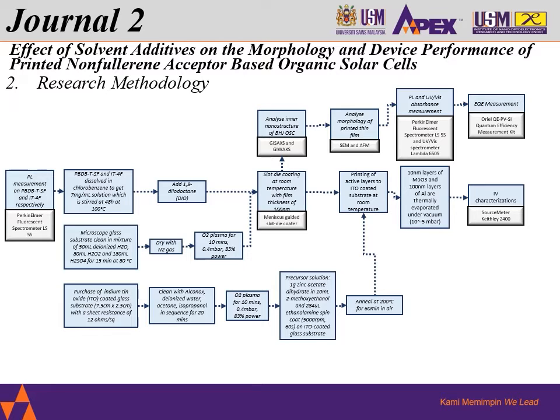And then in parallel, microscope glass substrates were cleaned in a mixture of 50 milliliters deionized water, 80 milliliters of hydrogen peroxide, H2O2, and 180 milliliters of H2SO4 for 15 minutes at 80 degrees Celsius. And this microscope glass later on will be dried with nitrogen gas and then oxygen plasma for 10 minutes. This is to further clean up the surface and enhance the wettability. And then once this substrate is clean, it is ready for slot die coating at room temperature, and a film thickness of 100 nanometers is achieved.